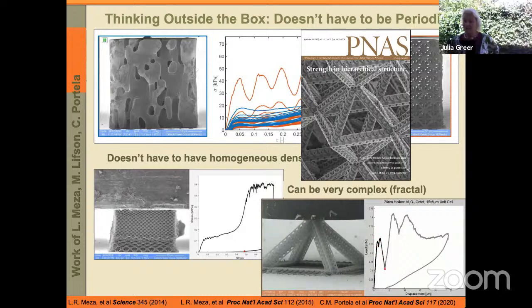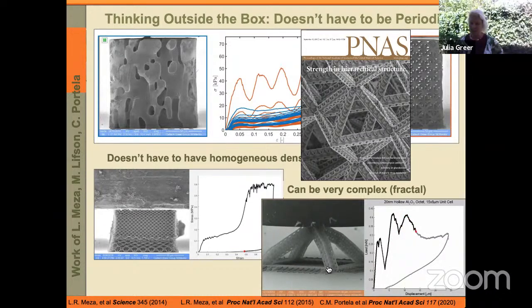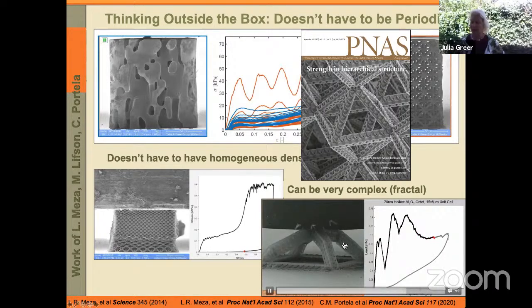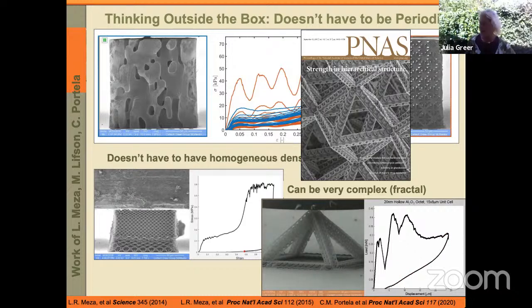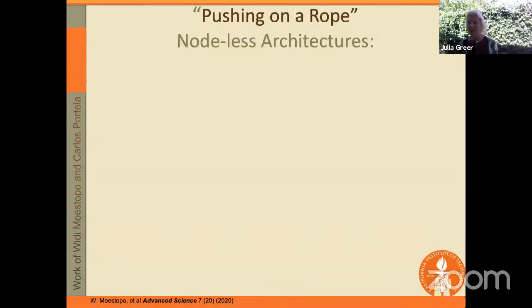Now, these architectures can be complex in the sense that they can be fractal, so that each individual beam is comprised of these cells. You can see already that each of these legs is starting to kink. And just as we're expecting it to fail right at those kink locations, because they're clearly very brittle, you can see the architecture fully recover. So what that's teaching us is that the size effect is very powerful and can indeed be proliferated onto the larger scales by this concept of architecture.